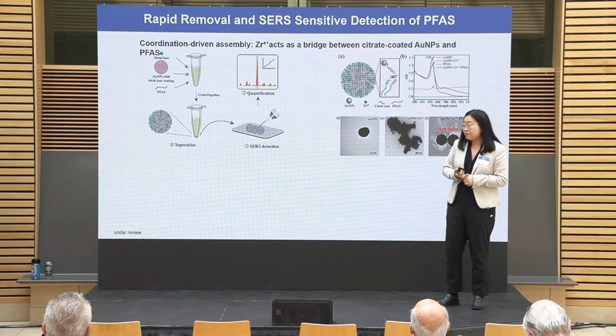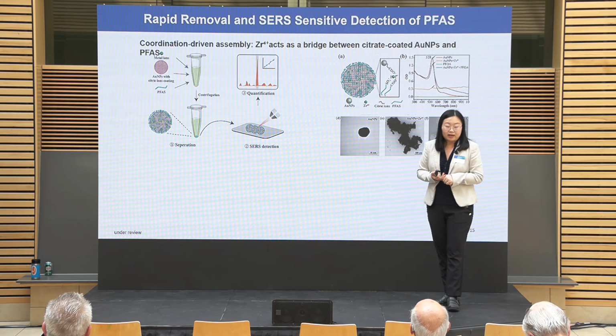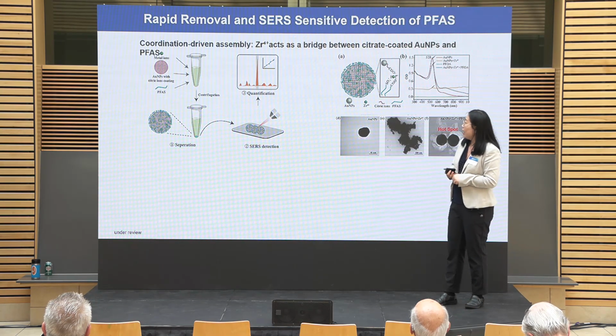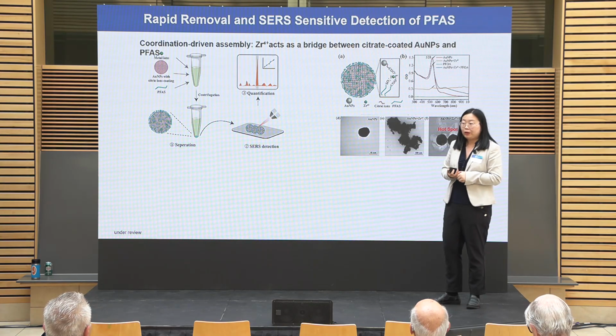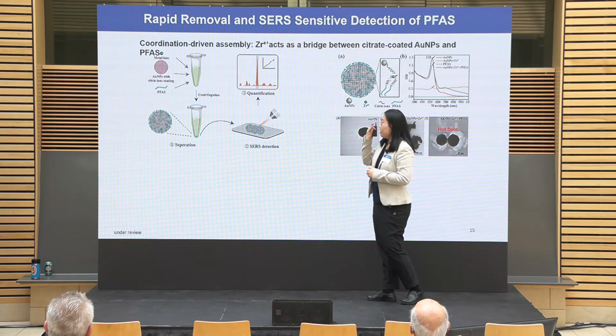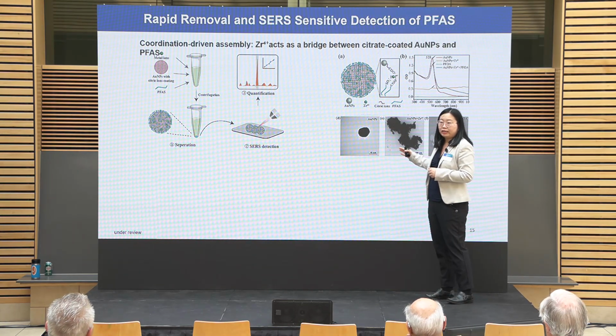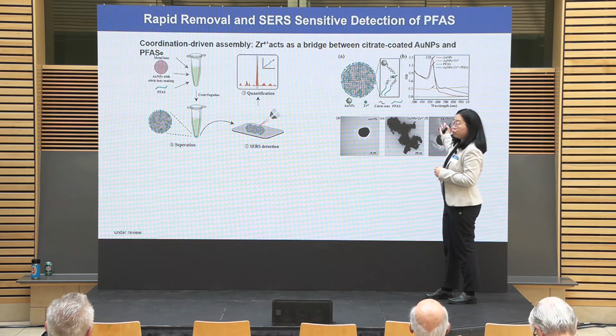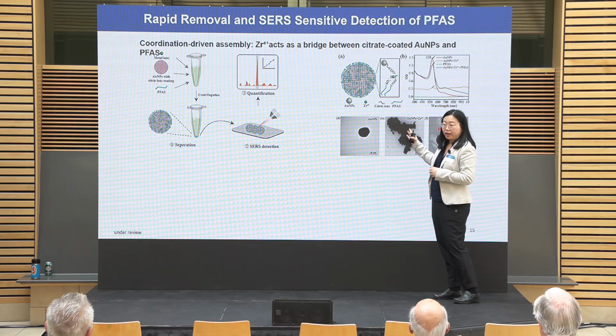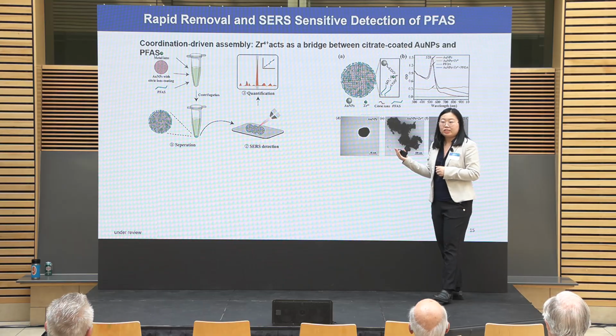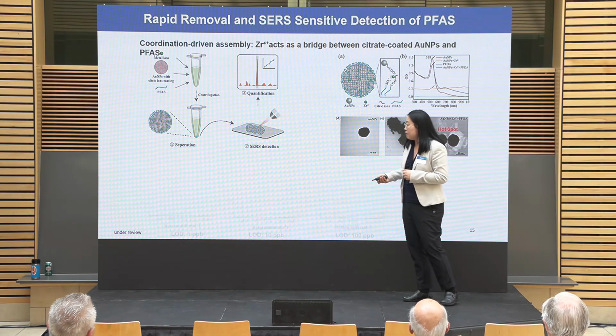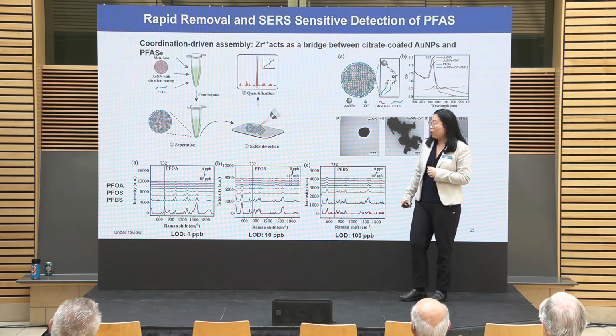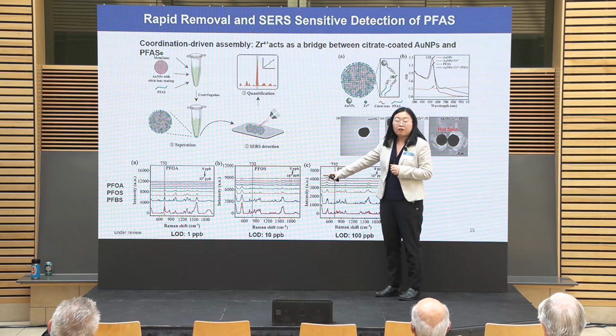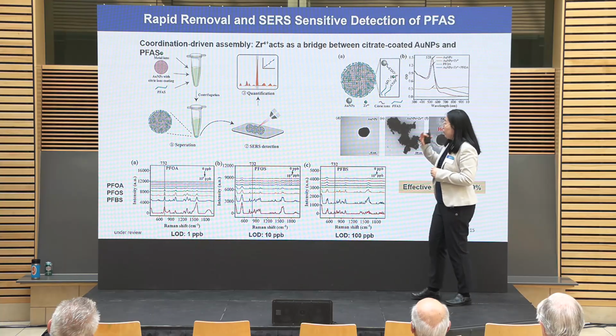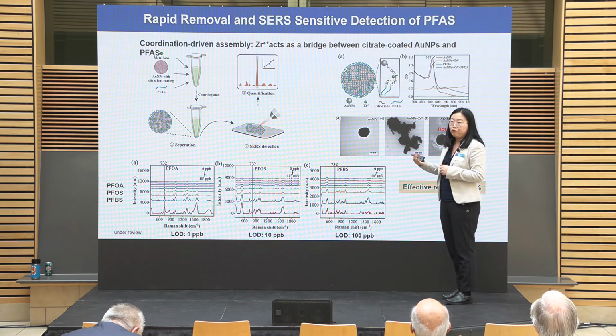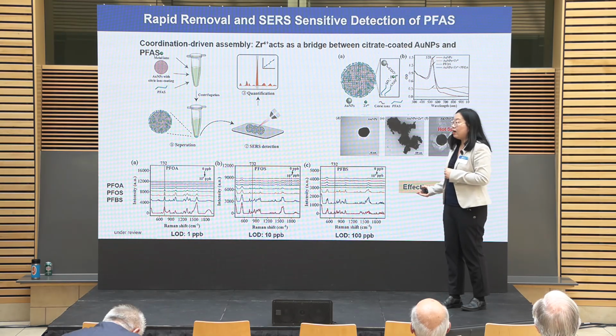Here, we developed a SERS method coupled with coordination-driven assembly. We use zirconium ions as the bridge between citric acid-coated gold nanoparticles and PFAS. In this study, we use citrate-coated gold nanoparticles as the SERS substrates. When we add zirconium ions, they cause nanoparticle aggregation due to electrostatic interactions. When we add PFAS, for example one type of PFAS, PFOA, it reduces the aggregation and creates a lot of hotspots in the SERS, which allows ultra-sensitive detection. Using this simple method, we detect different types of PFAS, including PFOA, PFOS, and PFBS. Our limit of detection is as low as 1 ppb. Using this coordination-driven coating, we can also simply remove PFAS from our water systems, and we got a removal rate higher than 99%.